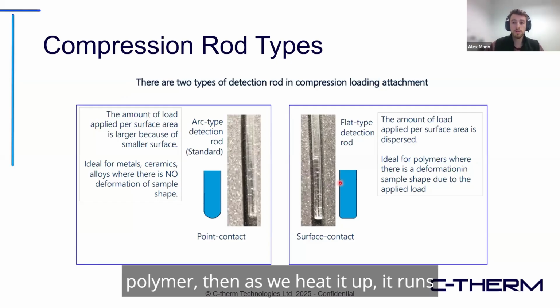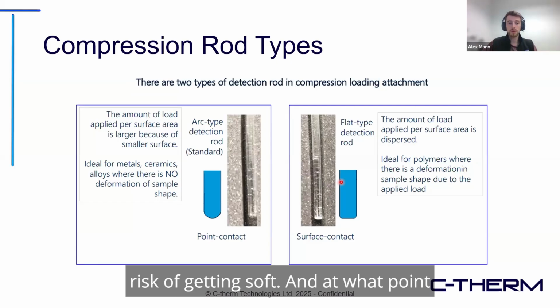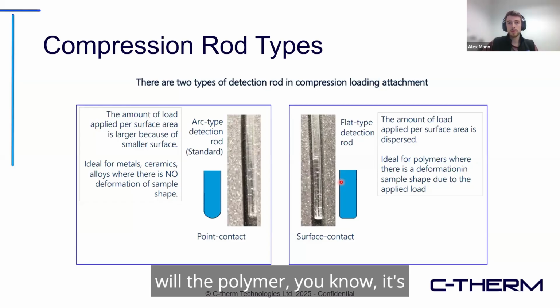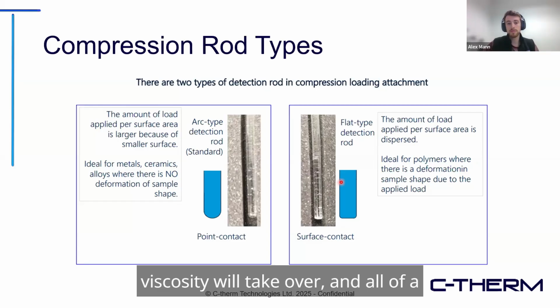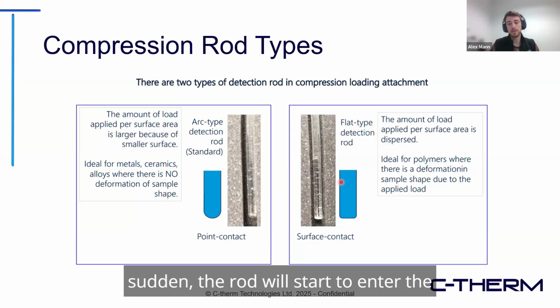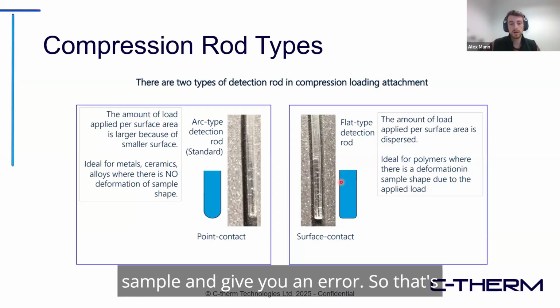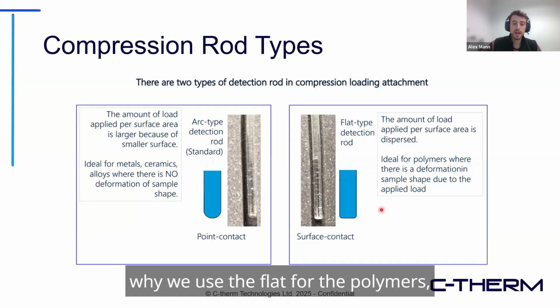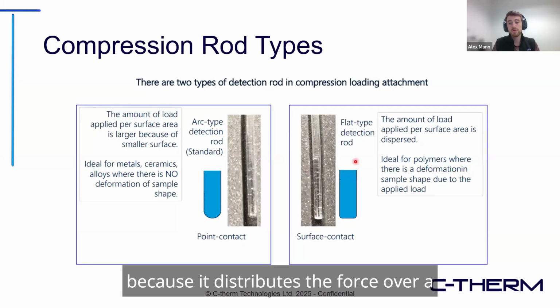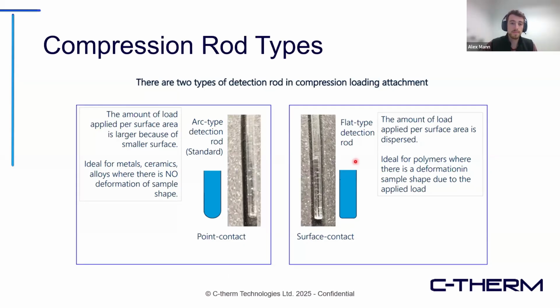However, if the sample is a polymer, then as we heat it up, it runs the risk of getting soft. At some point the polymer's viscosity will take over, and all of a sudden the rod will start to enter the sample and give you an error. So that's why we use the flat rod for polymers, because it distributes the force over a larger area.